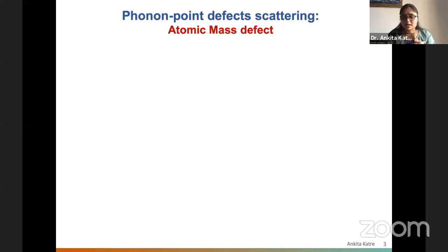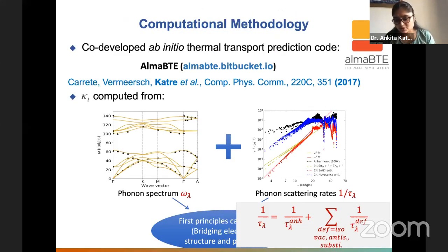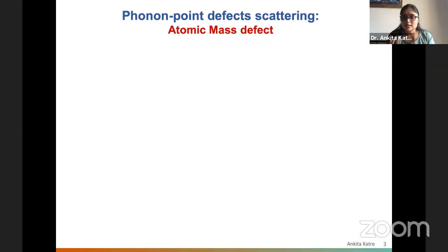Now, coming to the effect of phonon defect scattering: which defects, and in what approximations, or how simply can we include these defects in our calculations? The first step is to consider these point defects in the lattice as atomic mass perturbation only.